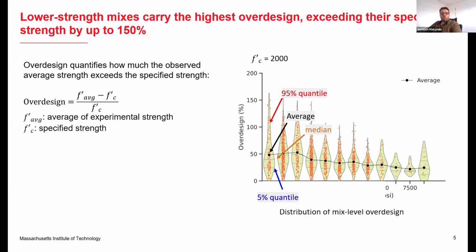And our analysis reveals a pattern here, and lower strength mixes carry the highest over-design, with some exceeding their specified strength by up to 150%. But for the higher strength mixes above 6000 PSI, the average over-design drops to less than 25%. And this is because the higher strength mixes are more expensive to produce for the ready-mix companies, and achieving a strength beyond the specification is already more costly for these productions.